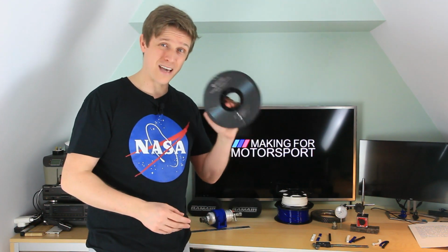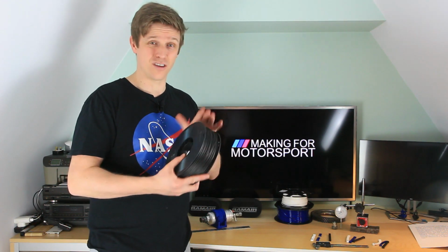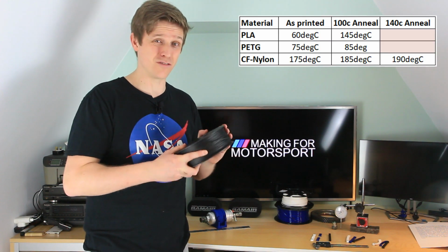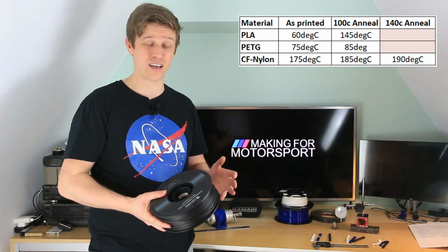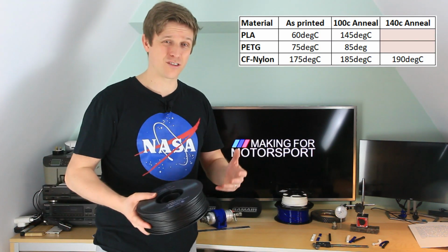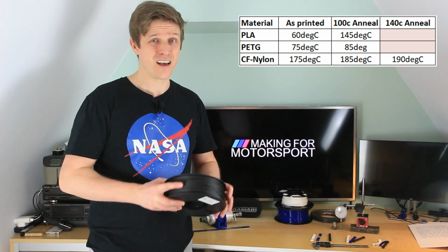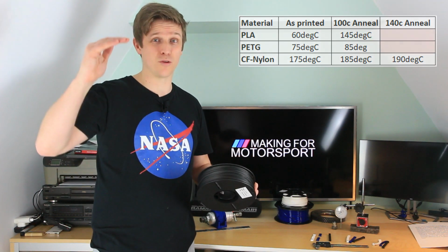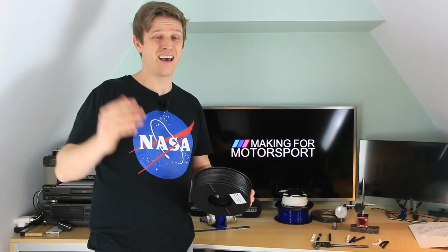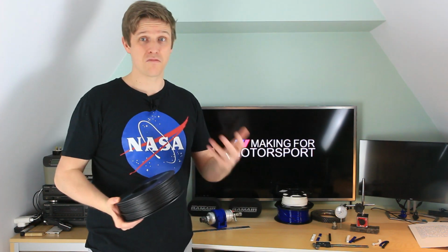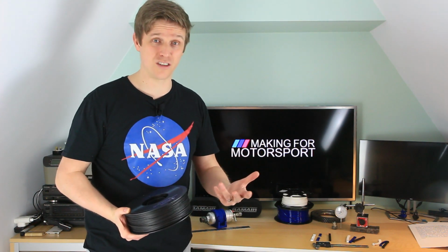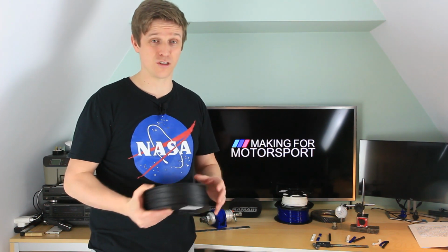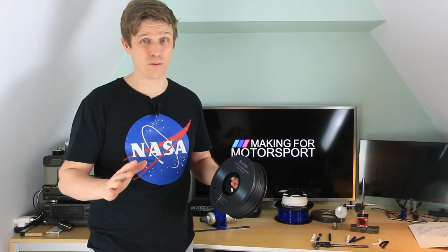Number two, you can anneal nylon. Certainly this one, it doesn't make much of a difference. I think we got 10 degrees difference out of it. So for all the extra faff, extra effort, it's really not worth it, because it's not going to bump you up into a higher temperature category. That said, it's very easy. There's no dimensional changes. It was still very stiff at 140 degrees. Personally though, I don't think I'll be bothering.